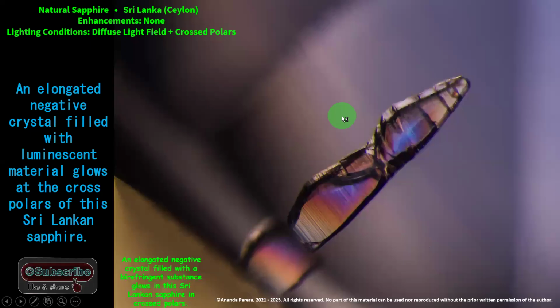Right, we are moving. Look at the first one. This is an elongated negative crystal. The lighting condition we use here is diffuse light field plus crossed polars, so there are two together. This is natural Sri Lankan sapphire. This elongated negative crystal is filled with luminescent material.